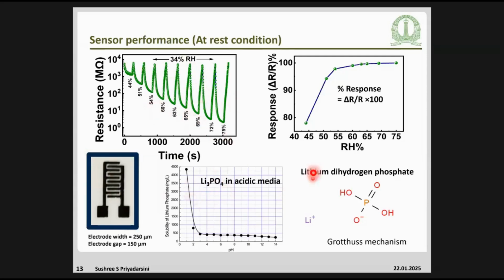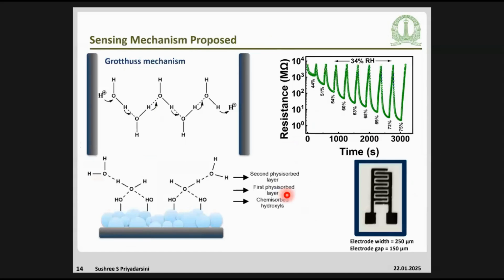So now what happens here is when you add some acidic media, that's what I was telling about, you form lithium dihydrogen phosphate at the local level, which generally attracts the humidity, and then it allows the resistance to go down through interparticle electron transfer. Now you can see from this particle structure that when you pass certain humidity, the chemisorbed hydroxyl gets absorbed. Then it first physisorbs a layer of OH. Again, it forms hydrogen bonding, and using that hydrogen bonding, the mechanism here was already proposed long time back by Grotthuss, and this is called the Grotthuss mechanism. What happens here is the hydronium ion goes from one water molecule to another water molecule, and you can see how it passes from one electrode to another electrode.